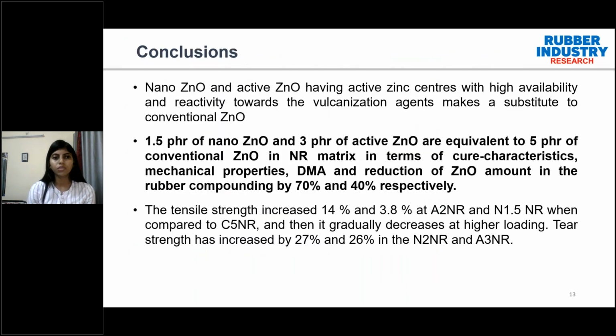So in conclusion, we can say that the nano zinc oxide and active zinc oxide, having high active centers, are actually giving a replacement for the conventional zinc oxide. That is, in a nutshell, we can say that 1.5 pHr of nano zinc oxide and 3 pHr of active zinc oxide are equivalent to the conventional zinc oxide in terms of cure characteristics, mechanical properties, and DMA, and that leads to a reduction of zinc oxide amount in the rubber compounding by 70 and 40% respectively.